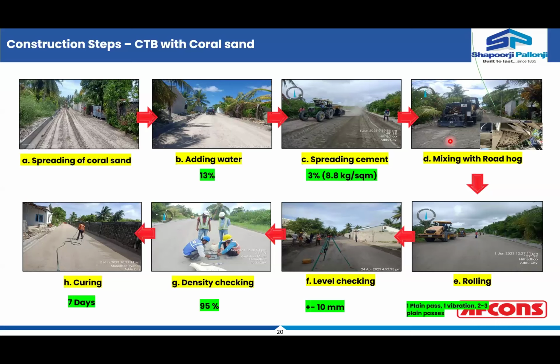So to ensure the control on the mixing part, the pulverization activity using the rotavator needs to be perfect, and then do the rolling part and then the testing to ensure that you achieve the required density. Of course, thereafter you have the curing period to be maintained. Generally, in this particular case, we have used 7 days curing using either the sand bed or sometimes a polythene sheet covered with water. So that is giving you an idea. Yes, you can replace with coral sand for a particular layer in the city roads at one of the projects in Mali.